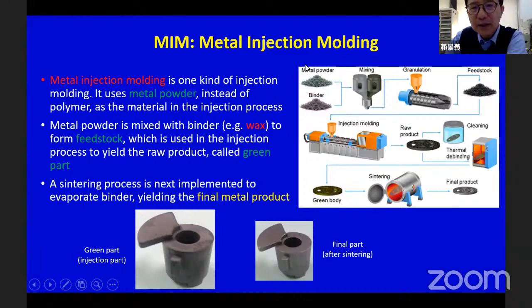For example, this is the metal powder, combined with binder. Usually the binder is wax. The wax and the metal powder are mixed together and become what we call the feedstock. The feedstock is sent into the injection machine to come out as the injection part. So metal powder is mixed with the binder first to form the feedstock, and the feedstock is used in the injection process, and we get the part we call the green part.